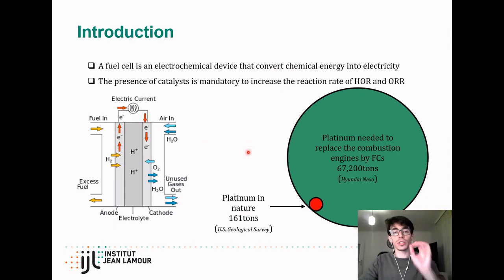And this is especially remarkable in the cathode electrode, where the oxygen reduction reaction takes place, since 90% of the total platinum content is located there. This is why most of the scientists who work on this matter try to focus their research on the development of new materials that are capable of reducing or replacing the platinum content in the cathode electrode of the fuel cells, where the oxygen reduction reaction occurs.